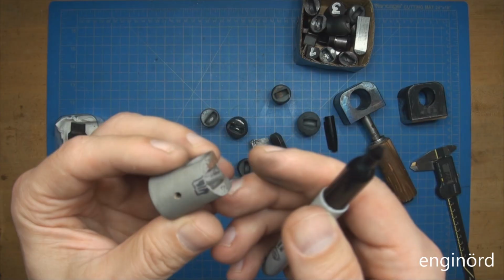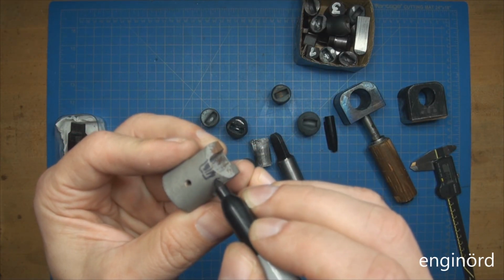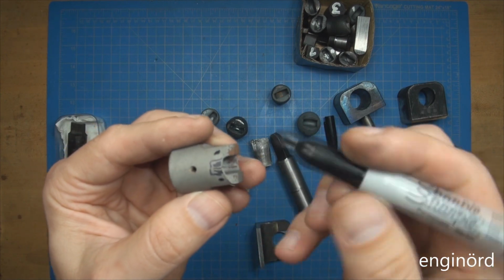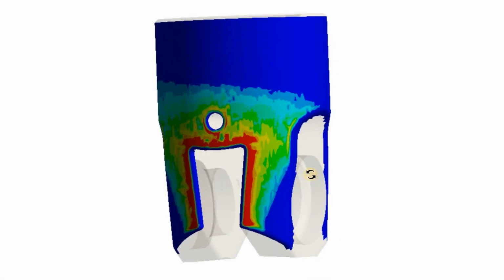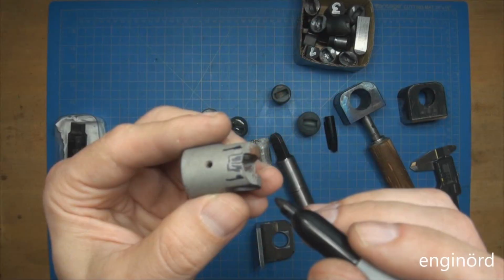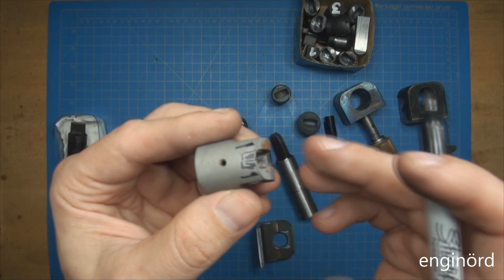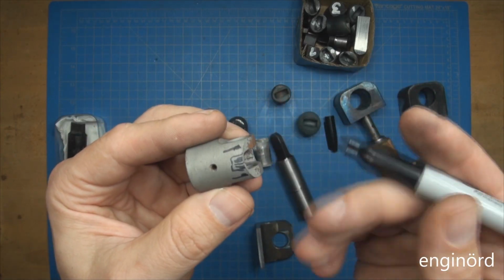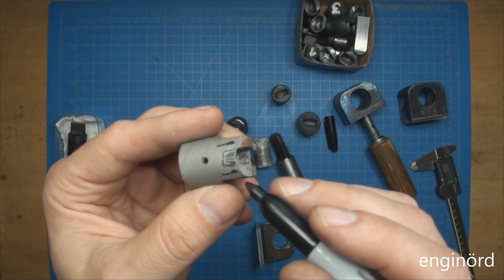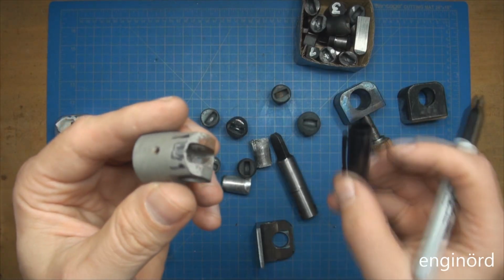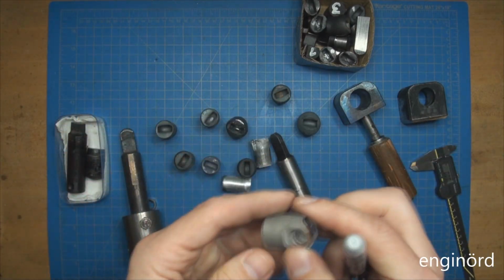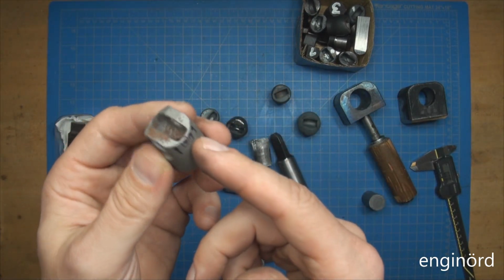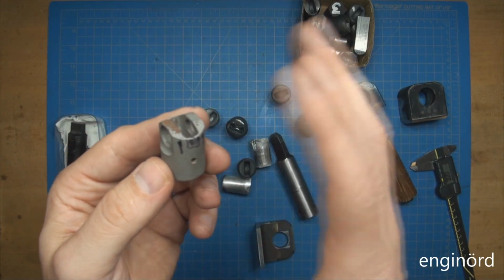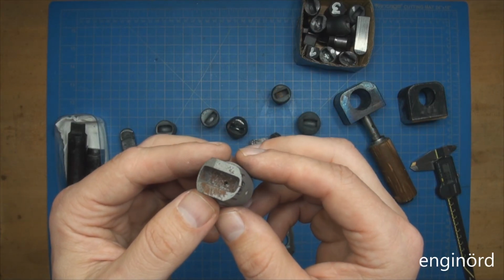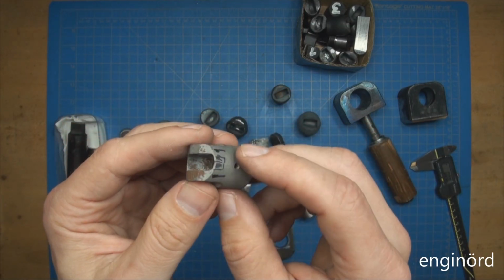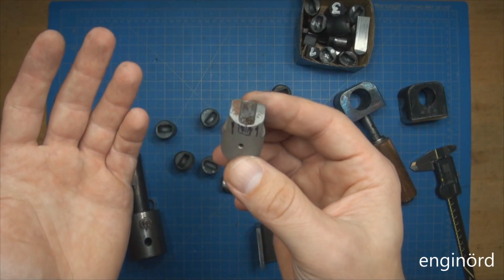Now, the drawback of that design is that when the tappet is working, there's high pressure in this and in this area. And so if I cut this section out, there will be even higher pressure in these areas. And I really don't have a good grasp of what is the highest pressure that I can allow in this design. According to FEA analysis, that maximum is between 5 and 10 megapascal, and the average is about 0.5 megapascal. Again, this is going to be hardened steel on aluminum. So if I go with the bladed design, I can just mill it from a stock. That will be basically just turning and milling operation. And again, the downside is higher contact pressure on the tappet and inside the housing bore. It might wear out the housing faster.